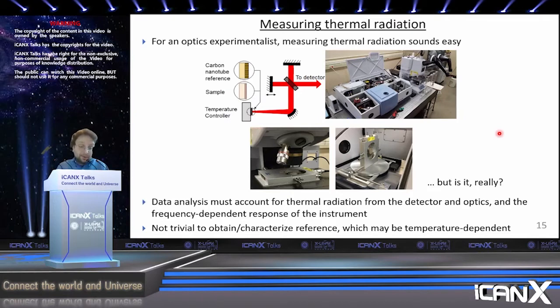An important reason for that is that the data analysis of your measurements has to account for not only the thermal radiation from the sample, but also the thermal radiation from everything else. Everything is thermally radiating. The detector is thermally radiating. The different parts of the instrument are thermally radiating. The walls of your lab, if you're standing next to it, you're thermally radiating. And so you have to account for all of that in an intelligent way. And also you have to account for the frequency dependent response of your instrument, because of course your detector doesn't have infinite bandwidth, your optics don't have infinite bandwidth, and so forth.